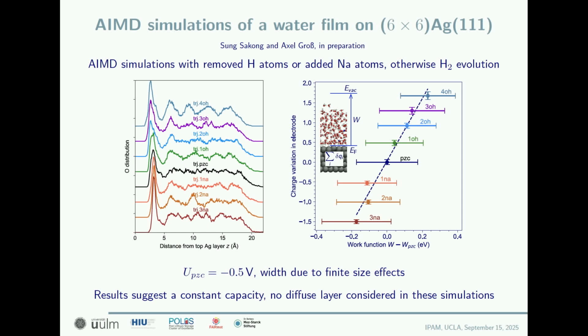And now here, I must say, this is hidden in this foil. I'm proud of DFT. Why am I proud of DFT? We now also did, I told my postdoc, a calculation of the most boring system. Why is that? Because silver is known to hardly bind anything on the surface. Even if you have electrolyte, it's so inert. That means, why did I want it? Because we wanted to make sure that we have a clear water layer there, and this is consistent with the experiment. Now, the potential of zero charge of silver 111 is minus 0.3 volts.